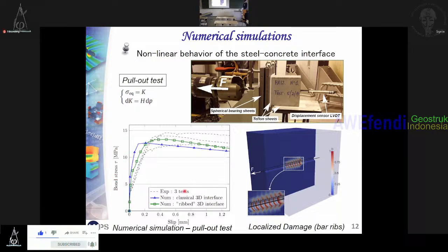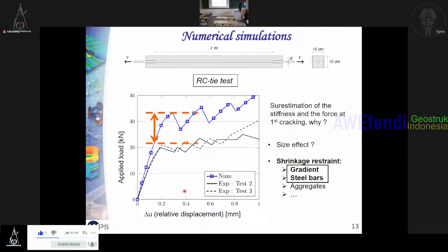So now if we come back to the concrete tie, we have the evolution of the force with respect to the slip between the rebar and the concrete. Here you have the two experimental results. If you do the numerical simulations, you see that you are overestimating the strength of the structure. Why? Is it a size effect? We know that if you change the size it matters, but here the size of the elements was not so different, and it was not that, in our opinion.